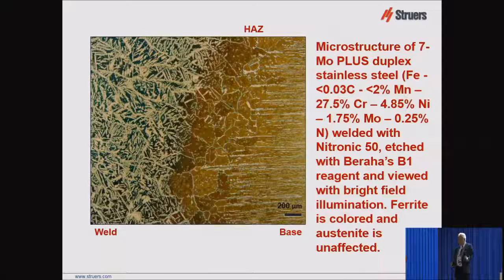Now, a previous speaker a little while ago was talking about duplex stainless steels. This is Carpenter's 7-Mo Plus, which is a typical standard duplex stainless steel. I wouldn't call it a hyper duplex, but 27.5% chrome, 4.85% nickel. You don't want to have enough elements in there that stabilize austenite because then you won't have a duplex structure. The idea with duplex stainless steels: there was a conference many years ago with people talking about stainless steels. I forget the exact year, but it was around 1980, I believe.